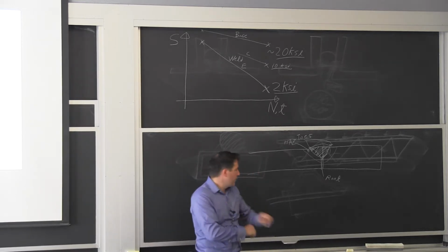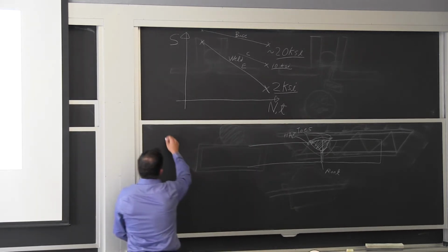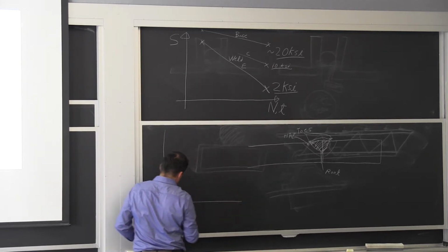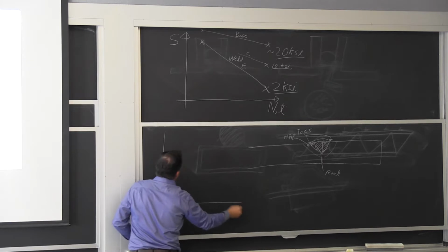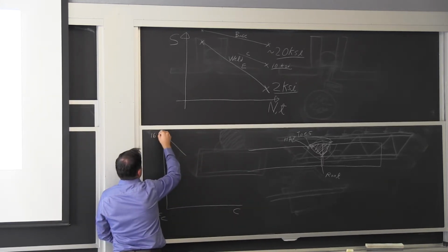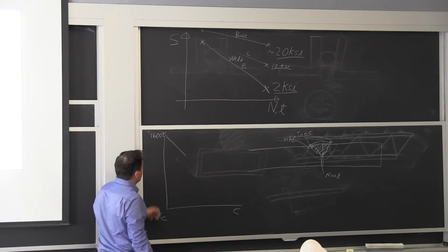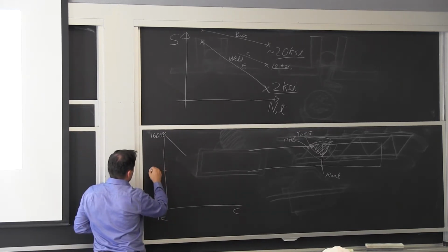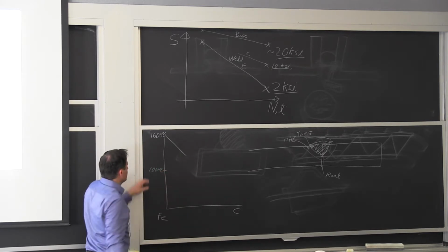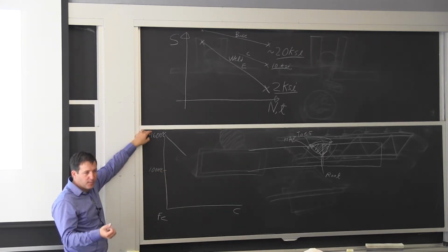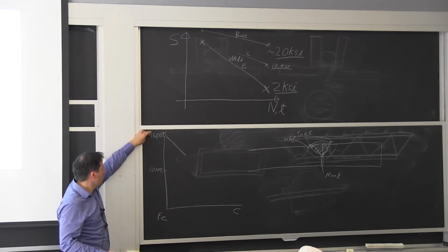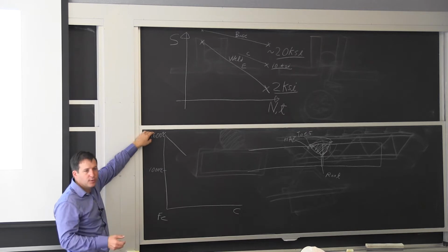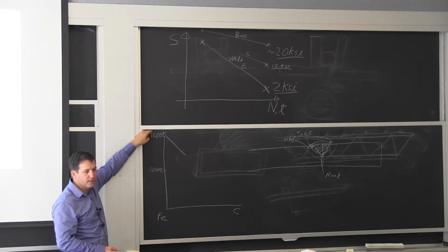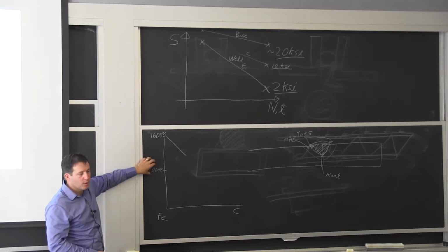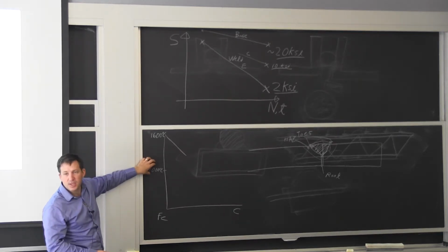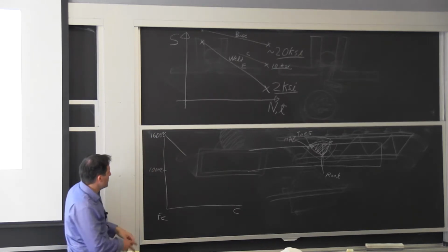Okay. So with respect to forming martensite, we almost have to go back to the phase diagram. The melting temperature is, say, 1600 degrees C or 1650, and the austenite zone is somewhere around 1000. So at the interface between the molten steel and the heat affected zone, it's a liquid in contact with the solid, you're exactly at 1600. But essentially you have a zone going away from the melted bead that is in that range where you form the austenite.